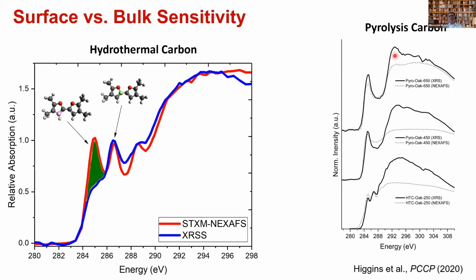So this is actually graphitic resonance. That can be seen very clearly in XRS, but not so much in XAFS, and that clearly tells us that basically this thing. And you see that this is more pronounced at 650 than 450, and that is because as you go to higher and higher temperature, the pyrolysis carbon or biochar becomes more and more graphitic in nature. More and more graphitic. Yes. And that's not happening on the surface at all.